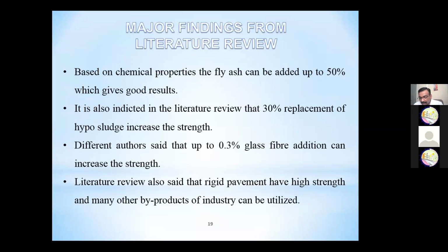Okay, now based on this rigid pavement, we have finalized some major outcomes. Based on the chemical properties, the fly ash can be added up to 50%, which gives good results. It is also indicated in the literature review, 30% replacement. The hyposludge increases the strength. Different authors say that up to 0.3% glass fiber addition can increase the strength. Literature review also says that rigid pavement has high strength and many other industrial byproducts can be utilized.